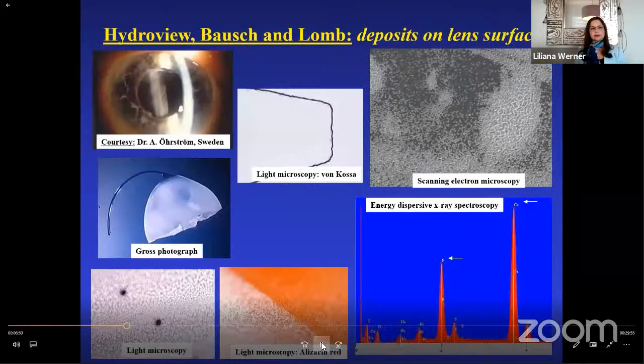Regarding the HydroView lens, the deposits were found mostly on the IOL surface, as demonstrated here by staining with alizarin red or processing through the Von Kossa method, which are both histochemical methods to demonstrate the presence of calcium. On the right, you can see the deposits under scanning electron microscopy, and a surface analysis technique such as energy dispersive X-ray spectroscopy can be coupled to electron microscopy to demonstrate the elemental composition of the deposits. You can see the presence of peaks of calcium and phosphorus in the calcified deposits.